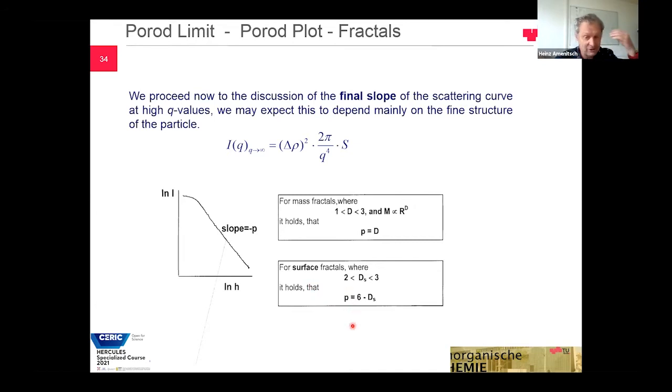What is also important is that this is so easy to measure. For instance, with chemical reactions, like in aerosols or aerosol-formed particles, or nucleation and growth, you have surface-limited reactions and so on. By the power law, you can measure the type of reaction, because there are lists in the literature where people made simulations of different reactions. So you get a different power law, and you can directly correlate the power law to the type of reaction really happening in your sample.